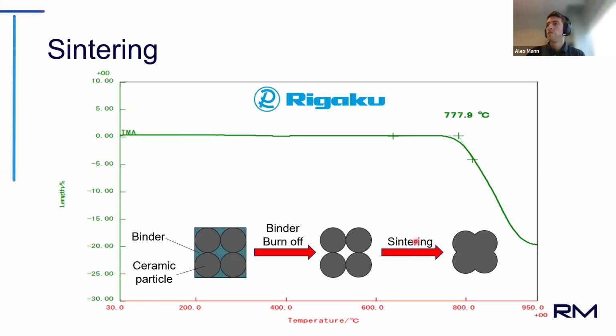As we can see here in TMA, we can actually find the point where this sintering begins, because as it densifies, it shrinks. So we say the shrinking starts at X temperature, and then we can calculate the final percentage. We can see here this one was just shy of 20% shrinkage. So you can use these to create your formulations or percentages of binder to ceramic ratio. You can try sintering and shrinking with different ceramic particle sizes. There's really a lot to go on here.